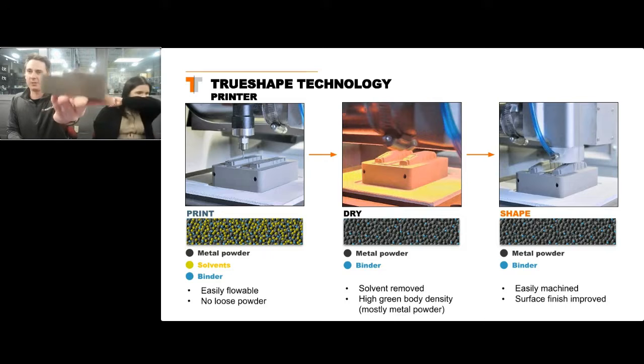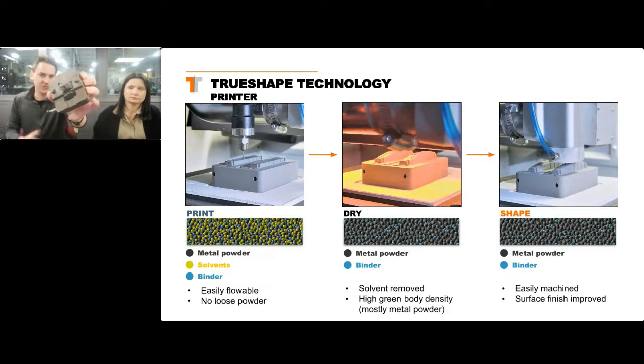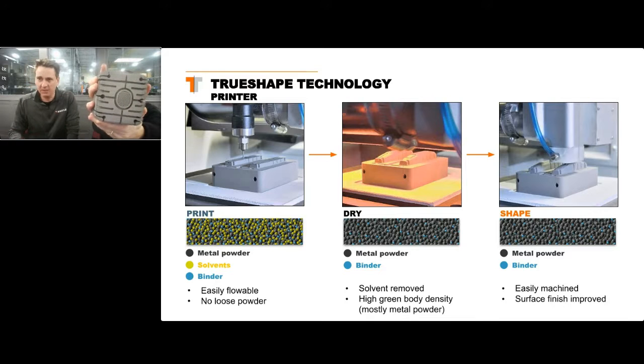Additionally, that's why when you look at these parts, people pick them up at trade shows all the time, and they say they can't believe this is printed. Well, it's a hybrid approach, so we're printing and machining, which is why you don't see those layer lines. It's why the details are so crisp. You want a good example here: the ability to print those really deep ribs because we're printing and machining, which is often what many of our customers are after to eliminate that sinker EDM time.